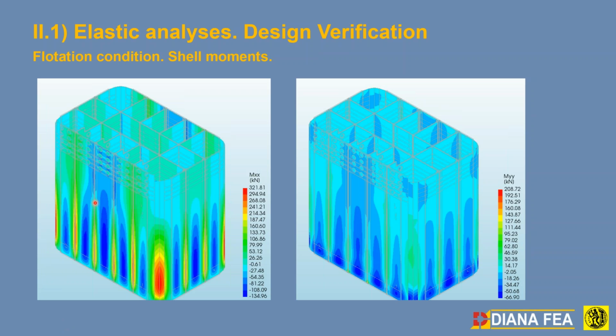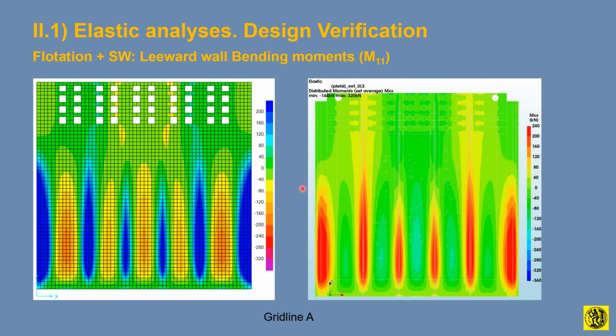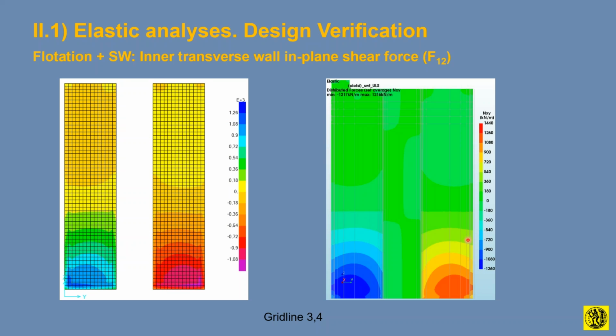The bending moments which are created, these are the local axis shell moments. Local axes run along the perimeter longitudinal direction and transverse directions. And then the local axes run in this direction in the transverse chambers here. So the bending moments are given in the vertical, causing vertical reinforcement, and horizontal reinforcement are given from the solution of Diana. And then we can see the check, if you like, between the two different softwares, the design software and Diana, and the results are similar. We don't have much difference. The two programs gave similar results.